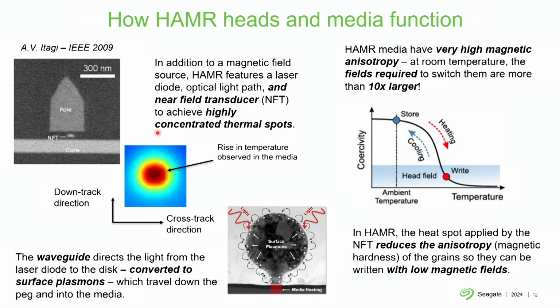We need to now provide an assist method that reduces this magnetic anisotropy, but only during the write process. So like I said, magnetic materials tend to lose their magnetization at high temperatures. So we can leverage this only during the write process and still have media that is very, very thermally stable at room temperature. So now we have, in addition to a magnetic writer, we have plasmonic elements, we have lasers that provide that excitation to be able to write the media.